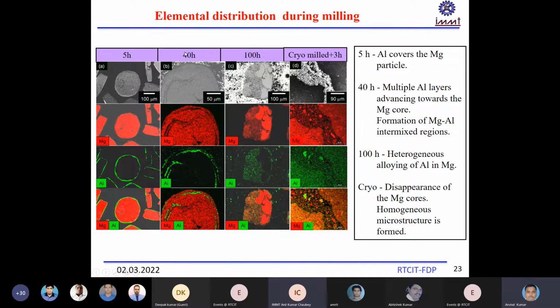This is the 5 hours, 40, 100, and then this is the cryo milling, and this is your original picture. This is the magnesium distribution and the aluminium distribution, and this is the combined magnesium aluminium. These pictures are going this side for different hours. So you can see that in the initial period of the 5 hours, this aluminium is not going inside the particles and not forming a complete solution.